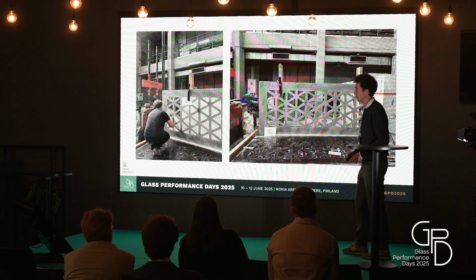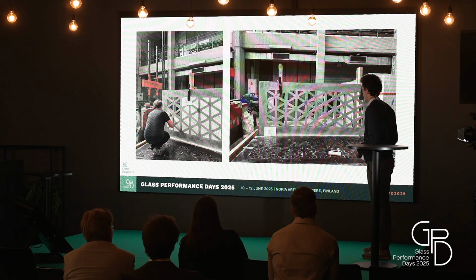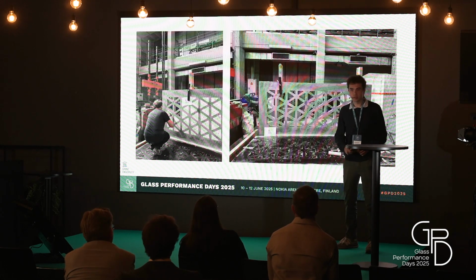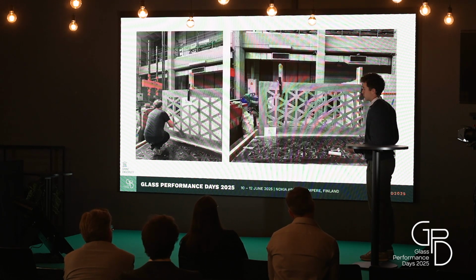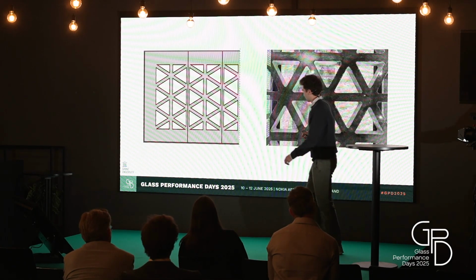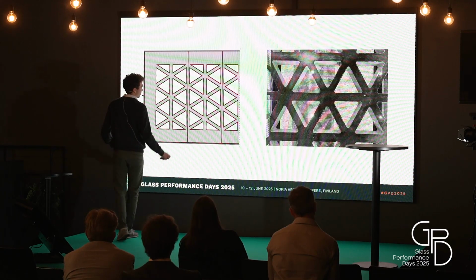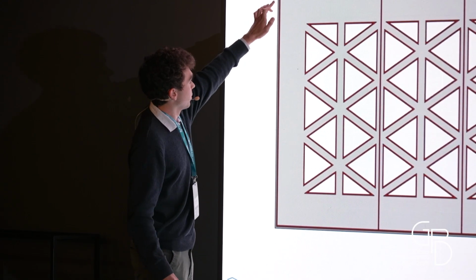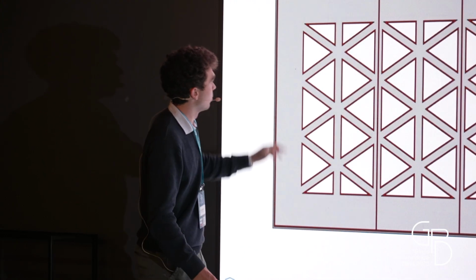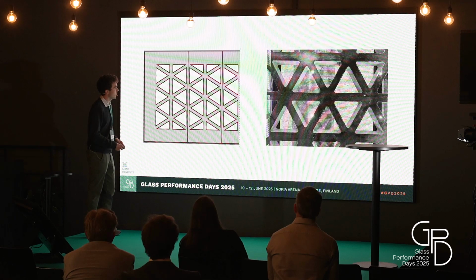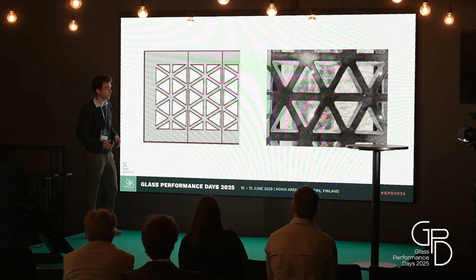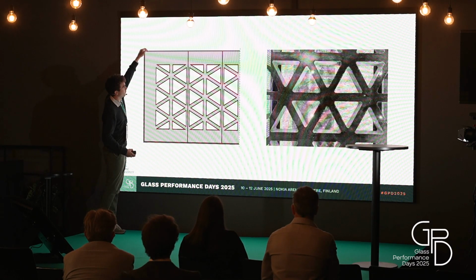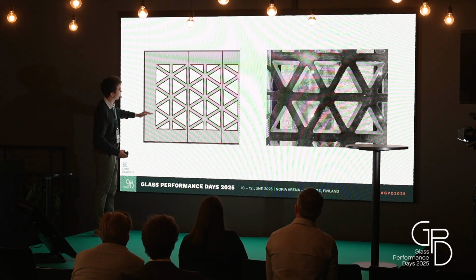Why vertically? Because of the bonding process. We used a 2-component epoxy, which was very, very liquid. And because it was very liquid, we could use that property for bonding. To be more clear, here you can see the shapes. We sealed all the edges on the red lines, on the outer side but also on the insides, with what we call a spacer tape. It was also transparent to make sure that when we pour it in from the top, it can just fill up from bottom to top for the full height of the panel.